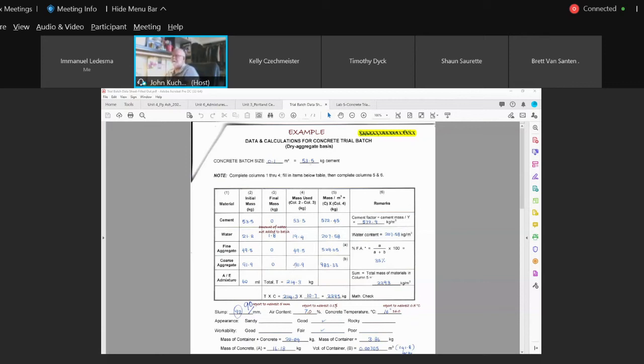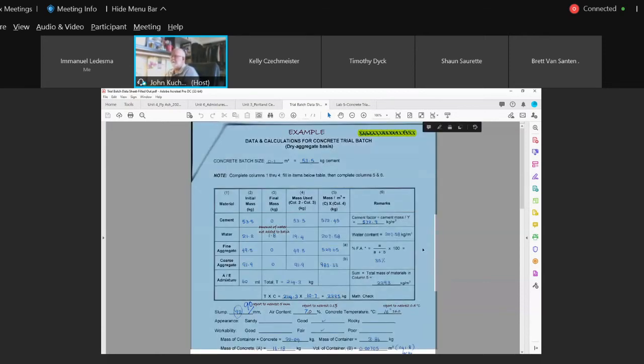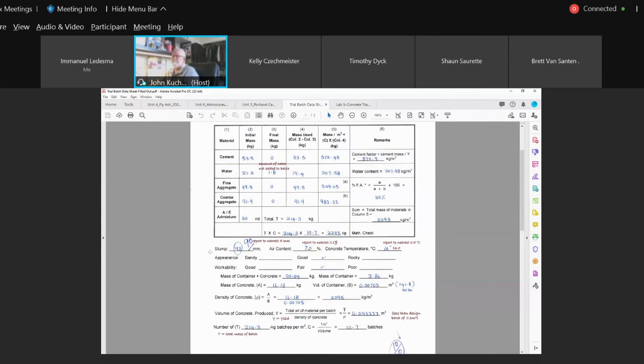So here in their mix design, the proportions they came up with, they did a slump test. They emptied the mixer, dumped it into the wheelbarrow, and sampled the concrete from there. Those of you who've done concrete testing in the field are familiar with slump. Here it's recorded to the nearest 5 millimeters, 90 millimeters. They wrote 92—you can't read 92, it's impossible. So I wrote in here: report to the nearest 5 millimeters. Slump is always recorded to the nearest 5.